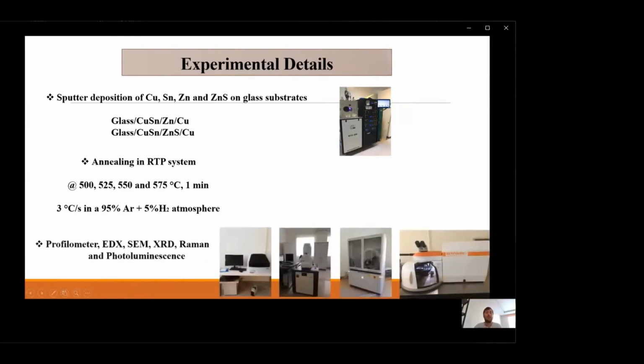And then finally, we analyze these samples with a profilometer to measure the thickness of the films, EDX to measure the chemical composition of the films, SEM, scanning electron microscopy, to investigate the morphology of the films, XRD to investigate the crystalline structure, and Raman also to investigate structural properties of the films. And finally, room temperature photoluminescence spectroscopy to investigate the optical properties of these films.